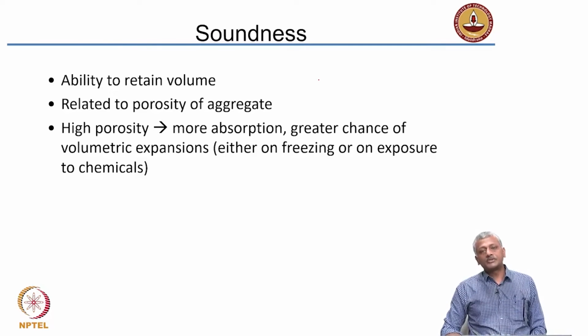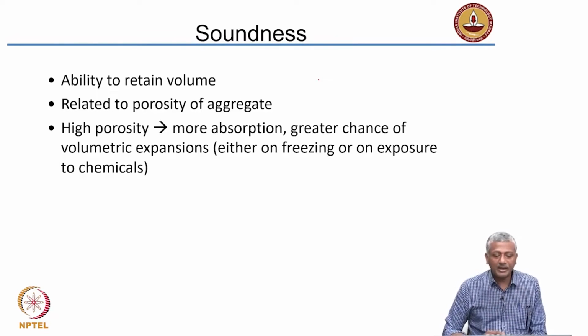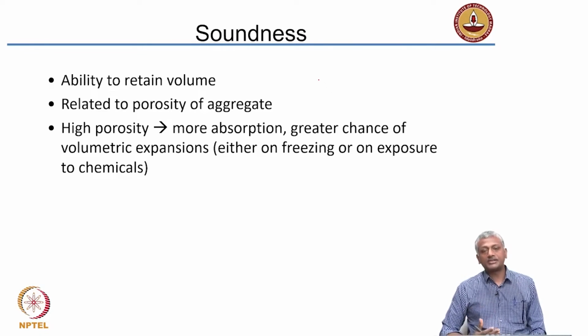Soundness is tested by using a magnesium sulfate solution. You dip your aggregate into it and you dry it, and you dip it and dry it for several cycles. What happens as a result is that in the porosity in the aggregates, you start forming crystals of magnesium sulfate inside that cause damage to the aggregate. Okay, higher porosity, you will have a greater chance of volumetric expansion. So, you need to restrict aggregate which has poor soundness.